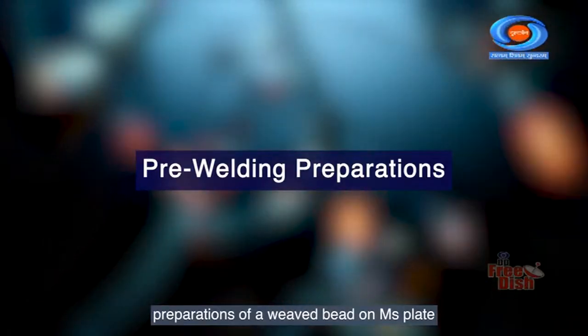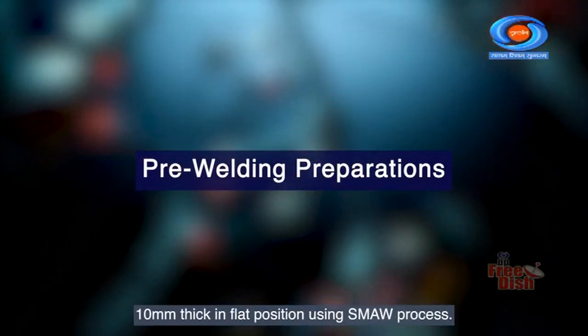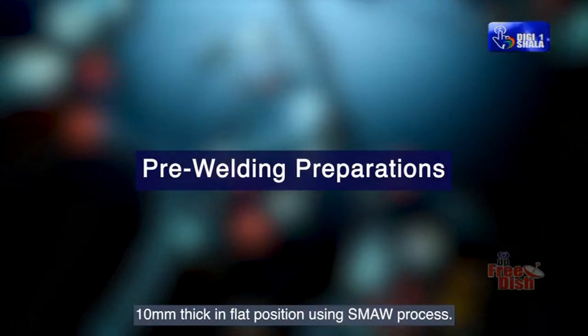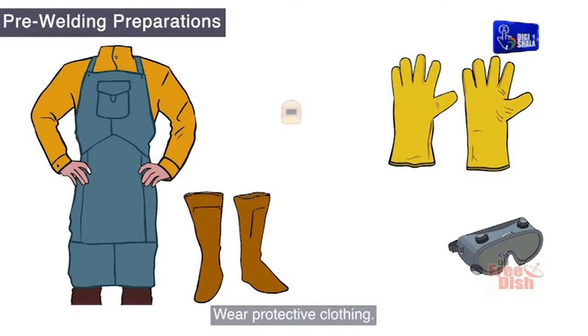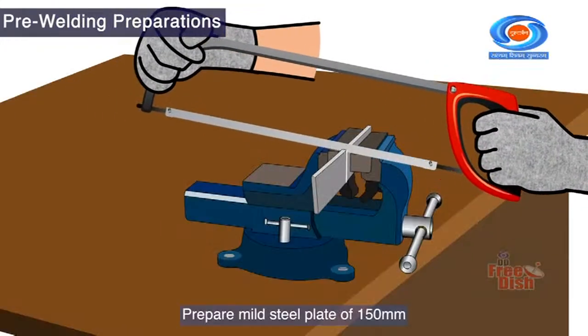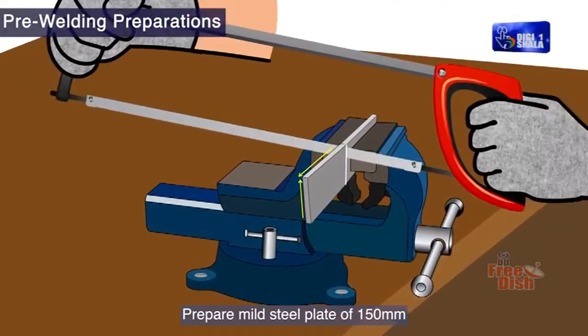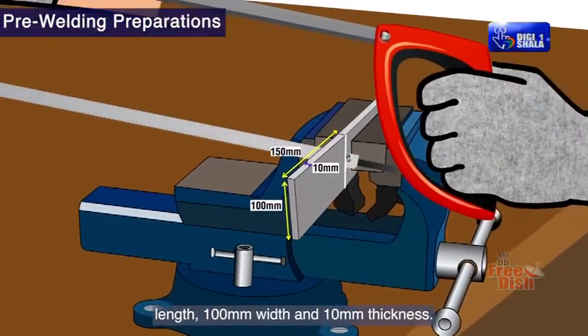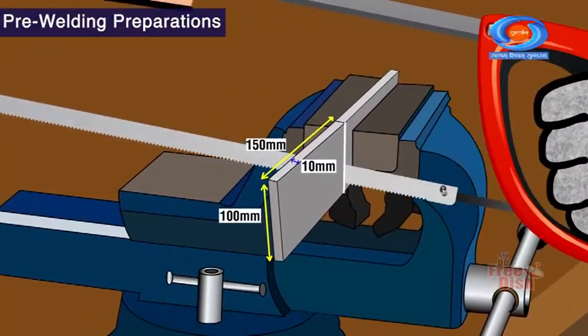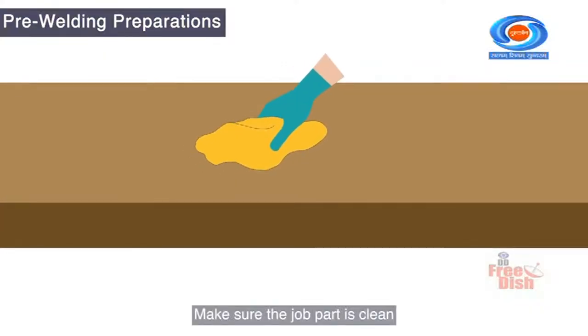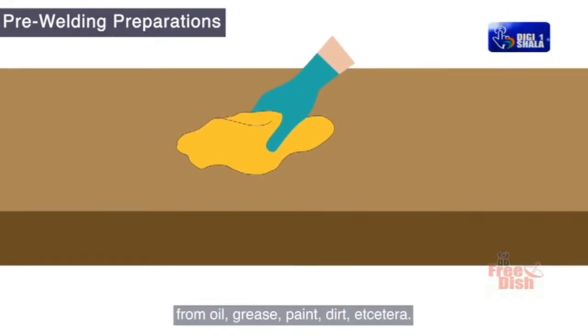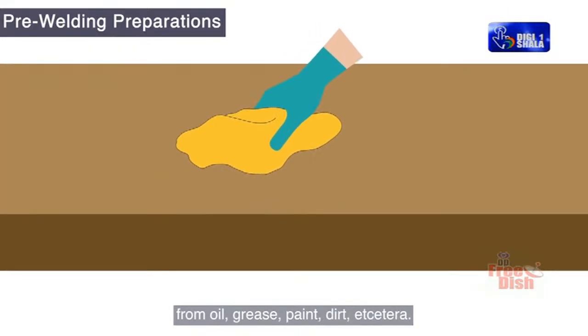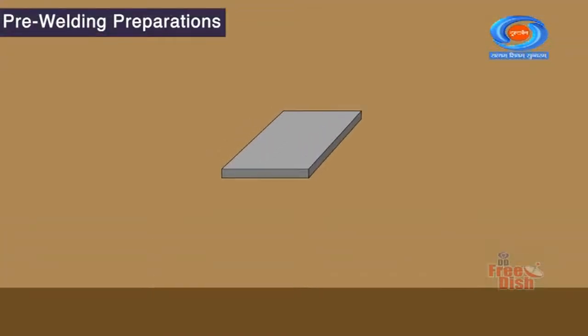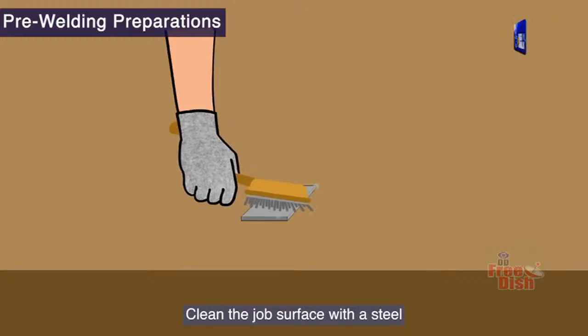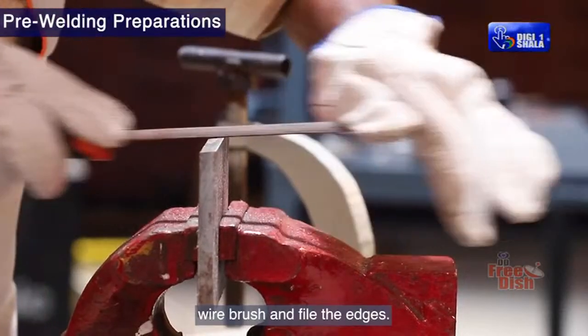Let us see the pre-welding preparations of a weaved bead on MS plate 10 mm thick in flat position using SMAW process. Wear protective clothing. Prepare mild steel plate of 150 mm length, 100 mm width and 10 mm thickness. Make sure the job part is clean from oil, grease, paint, dirt, etc. Clean the job surface with a steel wire brush and file the edges.